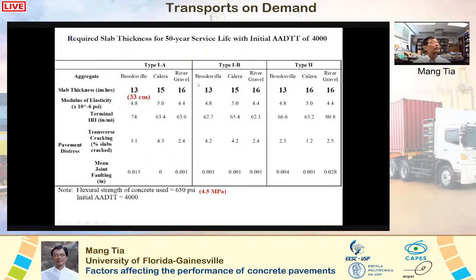So here we have the three designs, and we have concrete made with three different aggregates. All these concretes have the same flexural strength, but because they were made with different aggregates, they have different coefficients of thermal expansion and different elastic moduli, so their predicted performance is different. The results are fairly similar for the three different designs, but different from one aggregate to another. If we use this good aggregate with a low elastic modulus and low coefficient of thermal expansion, we only need a thickness of 13 inches.